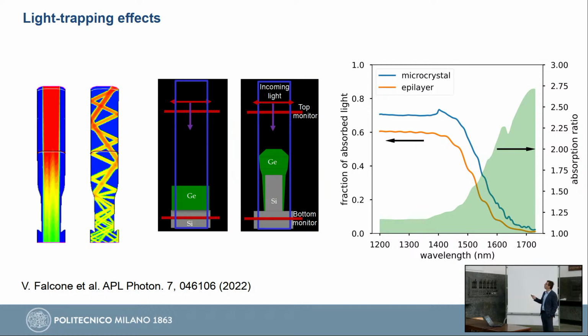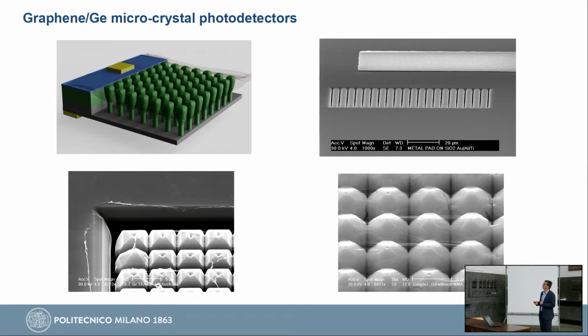And here, these are the two absorptions we get from the microcrystal and from the epilayer. And you see that indeed the microcrystal has a larger absorbance. And if you take the ratio, which is this green area here, essentially you have a stronger enhancement in the infrared than in the shorter wavelength part. So we decided to make a device out of this.